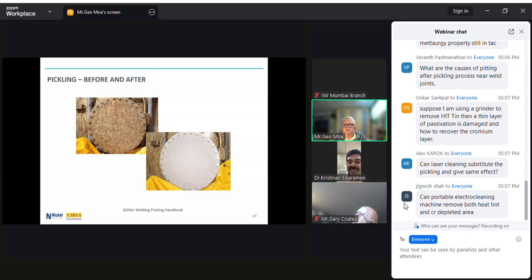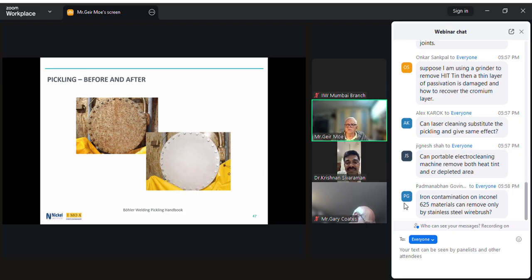Yes. So there is one more. Do we need to do pickling passivation for nickel alloy? Generally, you don't need to, because they are so corrosion resistant. If we talk about, say, a C-type nickel alloy, when you form a pit on a stainless steel, what happens in the pit is you're basically forming a hydrochloric acid solution. But a C-type nickel alloy is corrosion resistant to hydrochloric acid at room temperature.